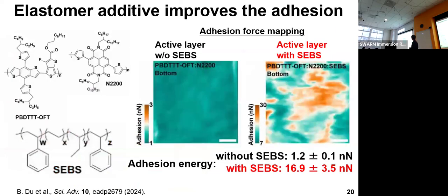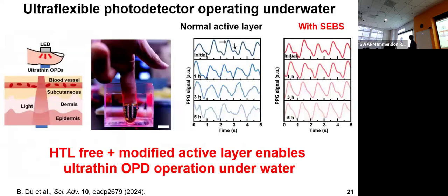And here is the adhesion force mapping of the active layer without and with SEBS, the elastomer. And you can see the adhesion force is sharply increased when SEBS was added to the active layer surfaces. So these increased adhesion forces beneficially improve the water stability. Okay. Then here we showed this kind of demonstration.